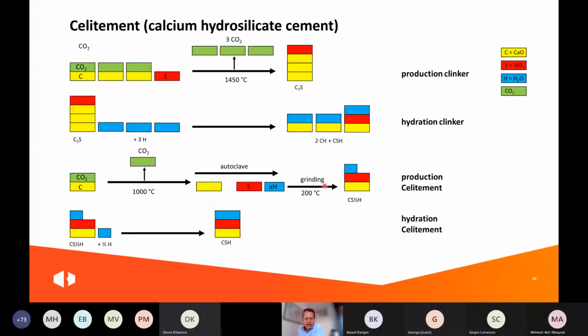But the process of this cement is quite complicated. You need an autoclave, and then you have to grind it again. Now that looks simple, but in practice this is a complicated process to get it stable and to make it on a large scale. The end products are of course also different. We have the CSH gel after reaction with water, that's in both cases, but with pure Portland cement you get 2 of those calcium hydroxide units which you need for the high pH, and here with Celitement you don't have those calcium hydroxide, so you end up with a low pH. You can process it like regular cement in concrete, so that's really an advantage compared with Solidia. But the low pH and the complexity of the process, that makes it difficult.